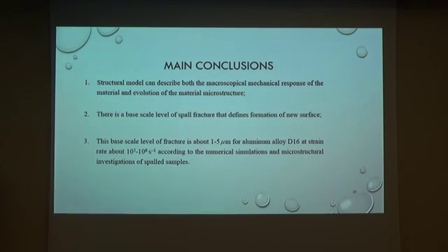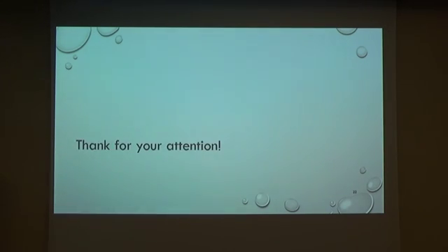There is some base scale level that we can predict by our models, and this scale level for aluminum D16 at these strain rates is about 1 to 5 micrometers. Thank you for your attention.